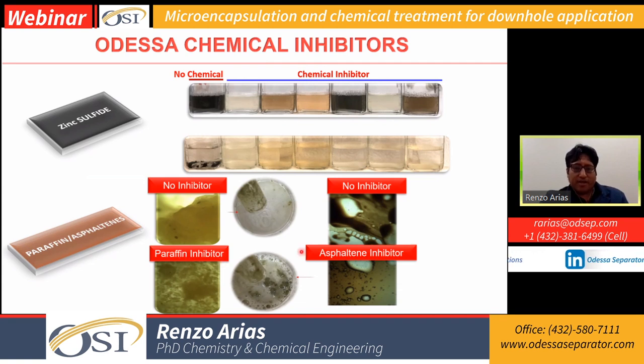So our paraffin and asphaltene inhibitors that we have in house are based on crystal modifiers, pour point depressants, and dispersants. That combination helps, as you can see microscopically, how the physical properties of the paraffin have been changed. Now you have paraffin that can be easily dispersed in your fluid. And like I said, sometimes one combination doesn't work, so you have to use different options for your system.